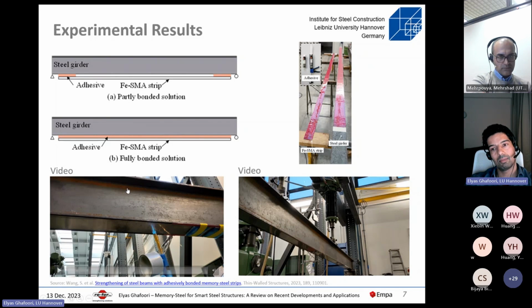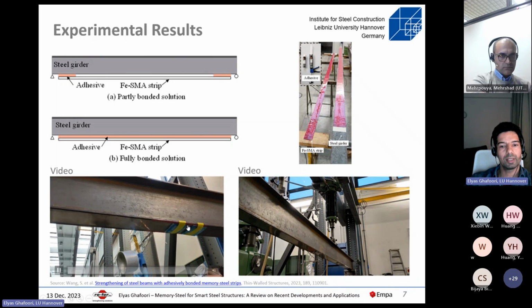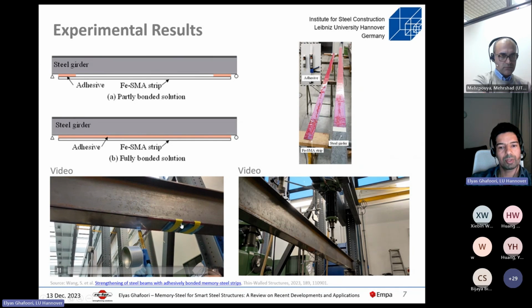So there we use mechanical anchors, and here we use adhesively bonded joints. There are two ways of applying adhesively bonded joints: by partly bonding at the very end, or by fully bonding along the whole surface. You can see the shape memory strip with Sika adhesive, and here is the activation process.